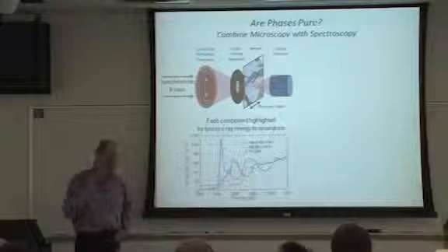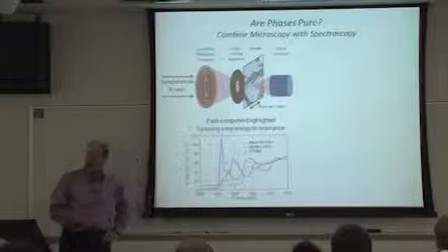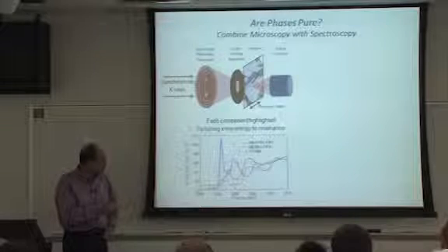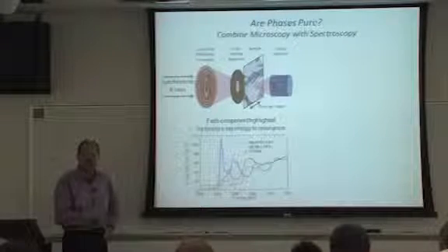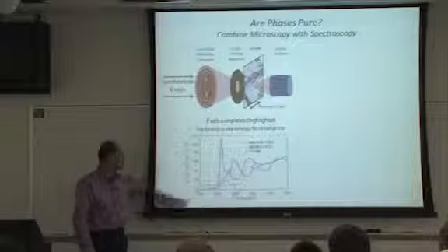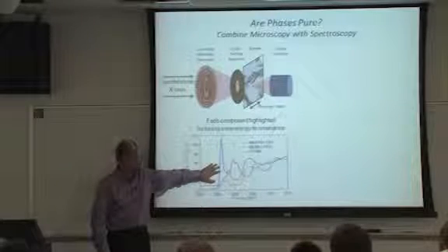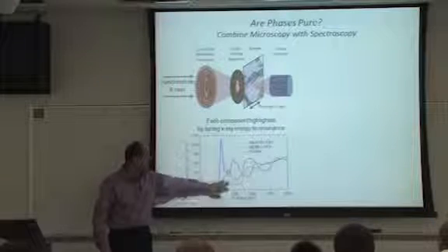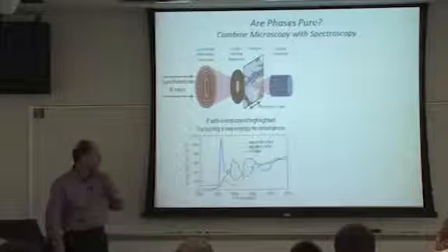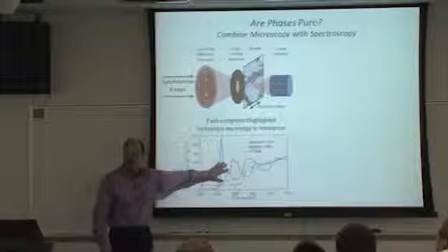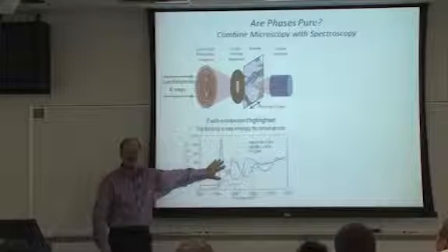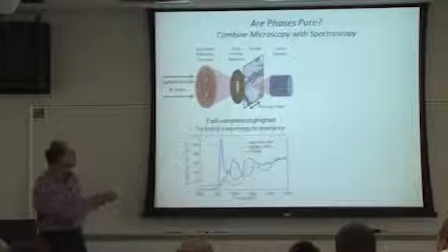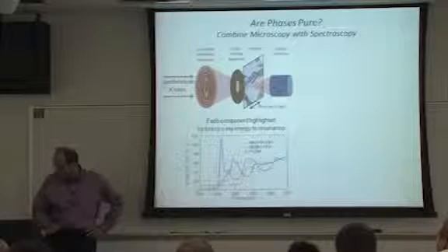So let's go to that question of how pure the phases are and see whether we can learn something from that. Here I now show absorption spectra of 3 prototypical materials used in organic photovoltaic cells. The blue one is PCBM, the red one is regioregular P3HT, and the green is the MDMO PPV. And you see they're all very different, so we can easily distinguish them. And we have good signal to noise, so we can do quantitative composition maps in the X-ray microscope.